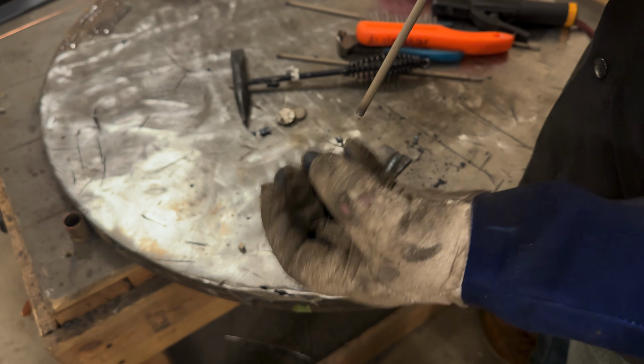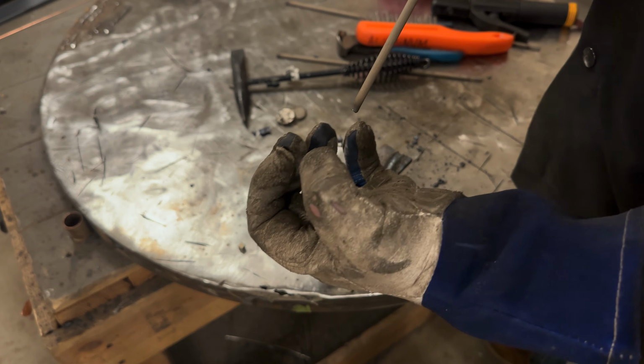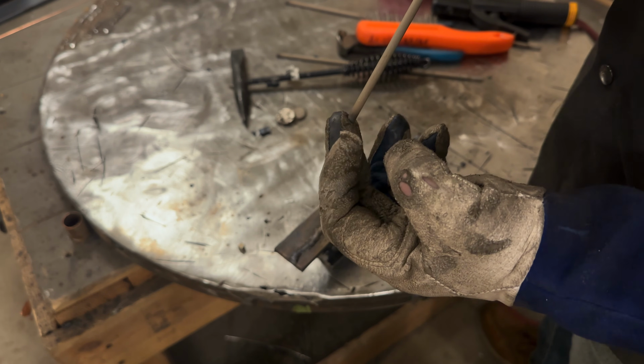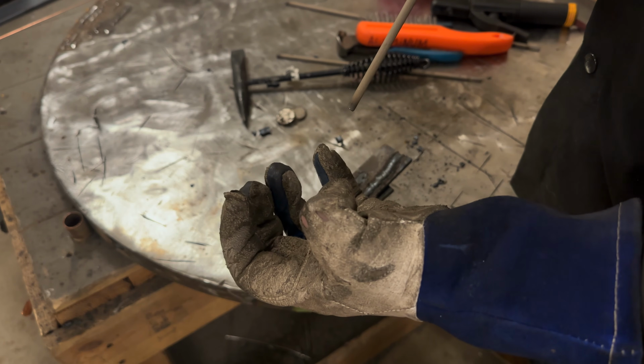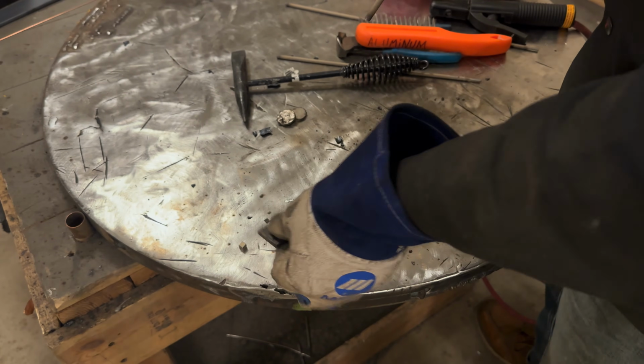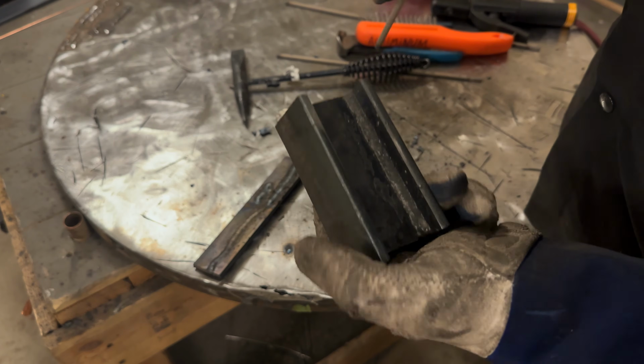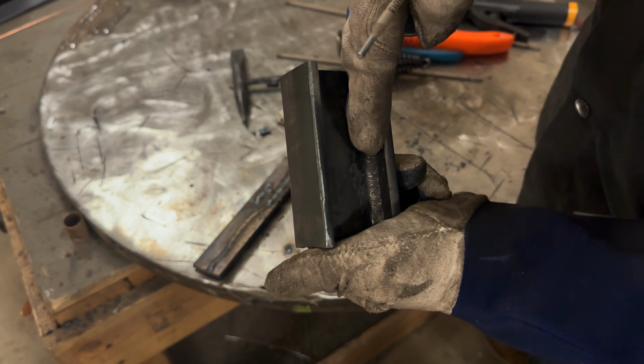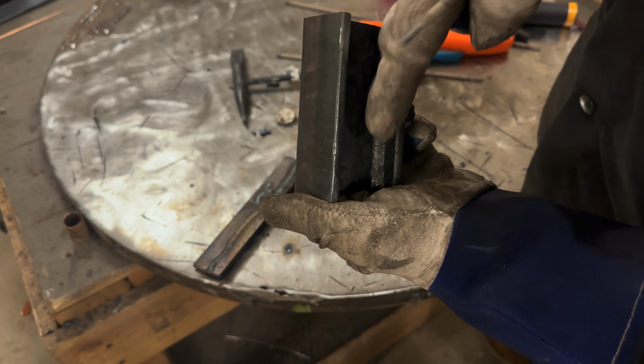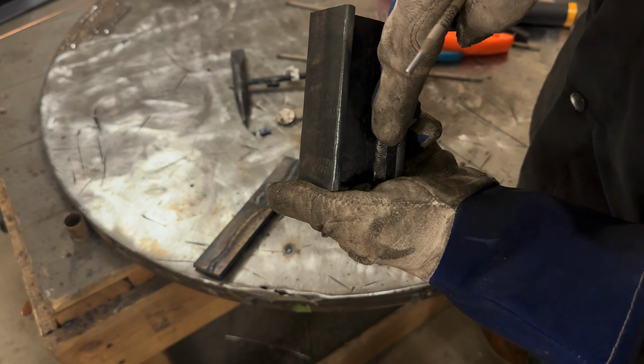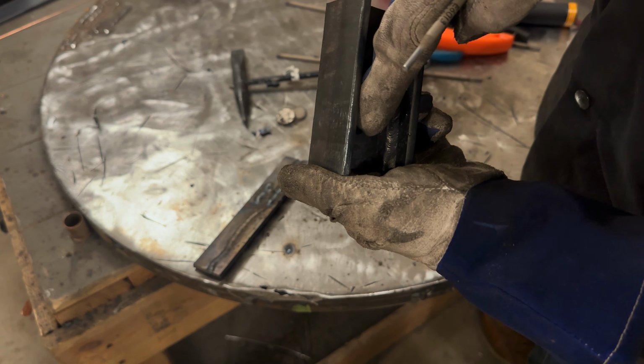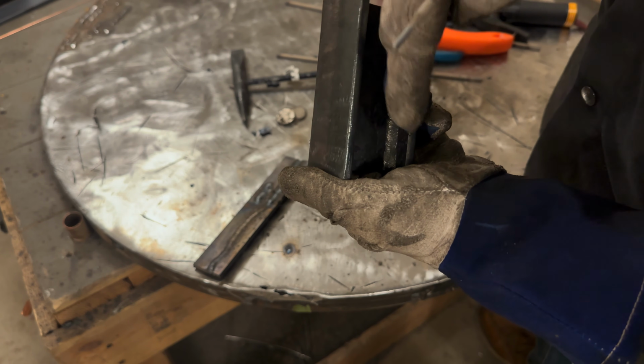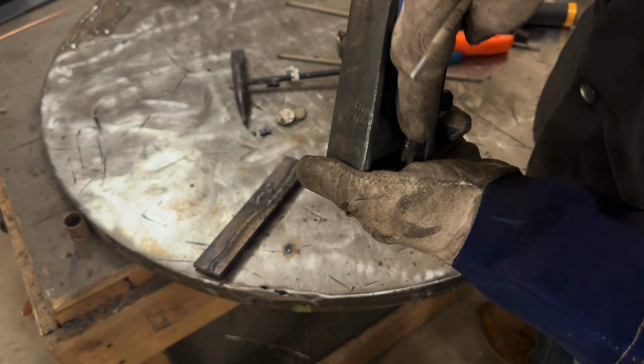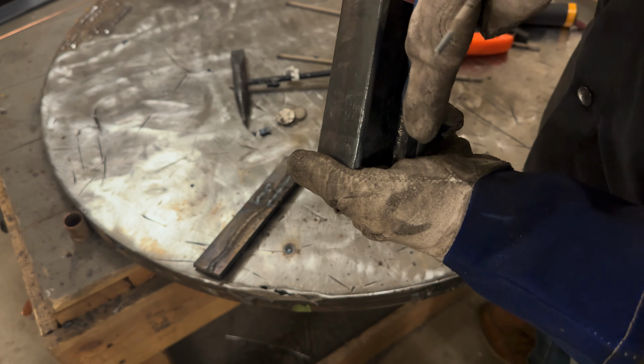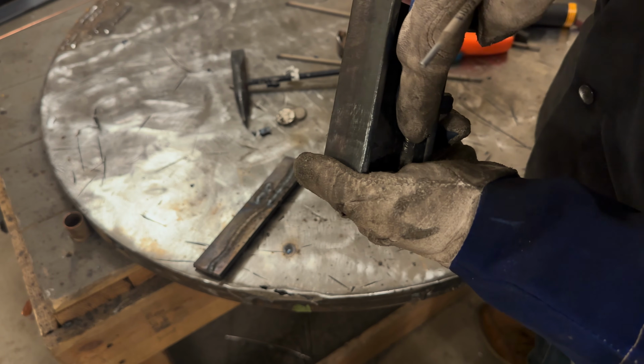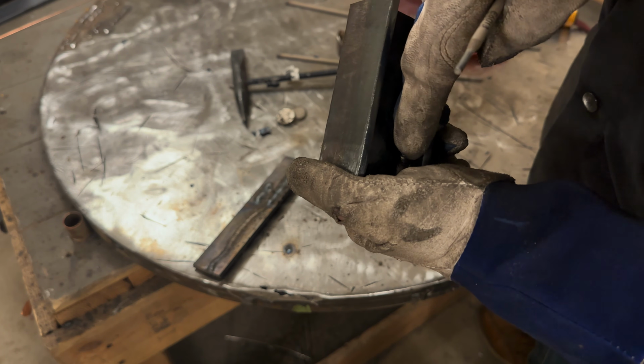And not only that, it's aiming for a very small tip, that sharpened tip of the tungsten, which is why sometimes on AC, when you're welding down on something like this with your TIG torch and you go on an inside corner like this and try to weld out, the arc may all of a sudden want to go to this piece and not this, and even if you tip the tungsten, it does not want to go to here. That can happen because the path to ground is disrupted, very much like with stick. And even on AC with TIG, you can get that.